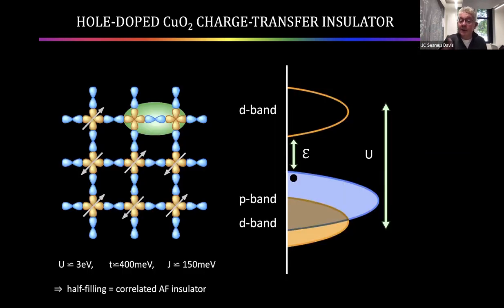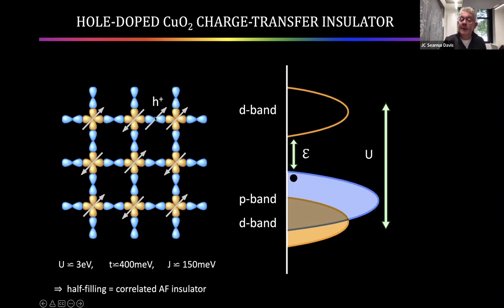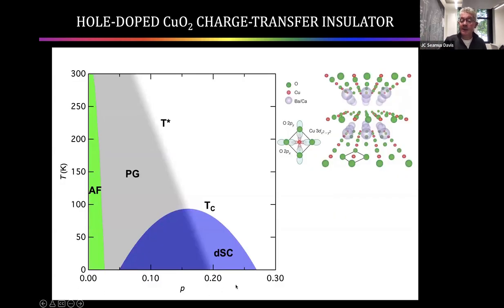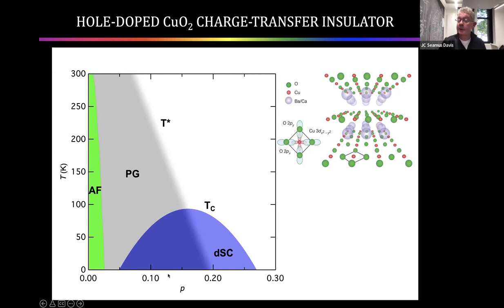These are insulators. How do you make them into conductors? You have to remove some electrons — by removing an electron from the top of the 2p band, which is the same as removing an electron from an oxygen atom. This creates some quantum mechanical state we don't understand. The axis of the phase diagram is the number of holes introduced — called hole doping. When there are no holes, the oxygen is in the 2p6 state. As we increase the number of holes, more and more electrons are removed from the oxygen atoms, the insulating state disappears quickly, and soon with enough holes the high-temperature superconductivity state appears.